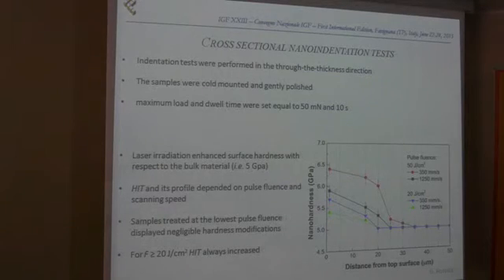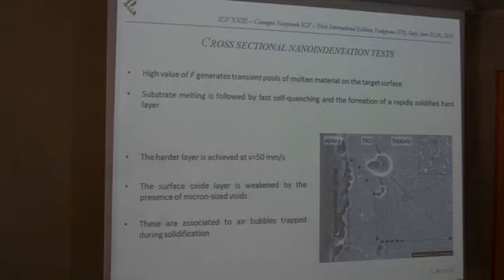We selected these particular parameters because even if from the previous results we saw that the lowest scanning speed was giving the best results, we had a problem with this particular test. In fact, as you can see here, even if the hardness was really increasing on the surface, we had the formation of an oxide over the top surface, which according to our tests was not suitable for adhesive bonding. And that's because, first of all, the drop of the hardness is very steep. So it means that most probably during the bonding process, this part of the material would be easily detached from the surface, or better, from the subsurface.